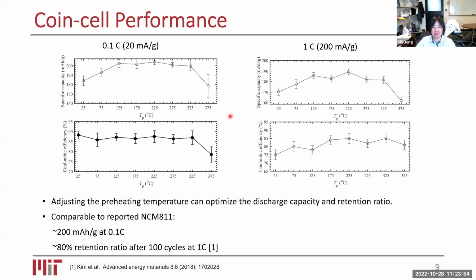So the take-home message from these figures is that compared to the reported value for the NCM 811, we can achieve comparable high performance, about 200 milliamp hour per gram. And also after 100 cycles, we can keep a retention ratio of about 80%. This all meets the standard set by industry. But we also can see for this particular project, such a high performance window is concentrated in between. And the two extreme cases that are presented indeed did not give us acceptable performance.